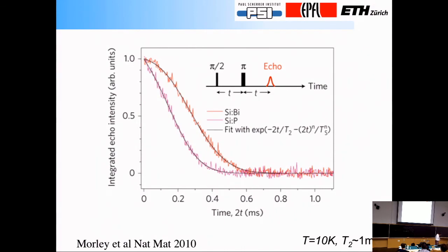And here are just some dephasing curves, Hahn echoes that we collected for, as it happens in this case, bismuth in silicon and phosphorus in silicon. What I really want to draw your attention to is, of course, first there is a decay, but the decay occurs over at 10 Kelvin. 10 Kelvin is a very, very trivial temperature to reach, and it's not a heroic temperature that requires a dilution refrigerator. You see here that these time scales, these decoherence times, are of order milliseconds.